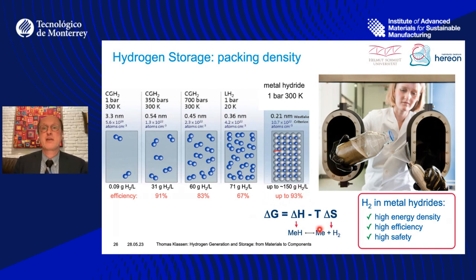The reason is basic thermodynamics. So the state of the system is determined by the chemistry delta H, the enthalpy, and the entropy. So that's the measurement for disorder. So, and with the temperature, you can tune which has more influence.